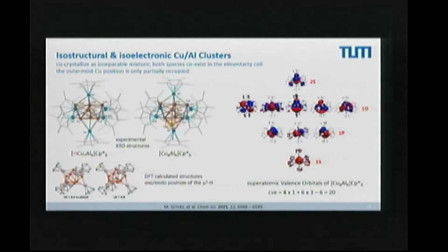a 19 electron system. Now recall, what happens in the periodic table if you go to a situation 1 electron short for shell closing? You will have a very highly reactive radical. And this is exactly what we have here. So this is why a copper 9, aluminum 6 would capture a hydrogen radical from wherever it can get it, from the solvent or from the hydrogen. And we can do that. We can deuterate the solvent. And if we do that, then we have a D on this position.